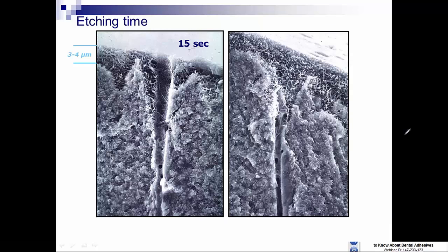If we etch a dentin for about 15 seconds, and we're talking now mid-coronal to deep dentin, the 3 to 4 micron layer of dentin is demineralized, and in these beautiful micrographs, courtesy of Marcus Vargas from the University of Iowa, we can see the collagen fibrils frozen in space that we're going to try, through the moist bonding technique, to interpenetrate with these resin monomers. If we etch longer, however, in this dentin, we etch at least double the depth.